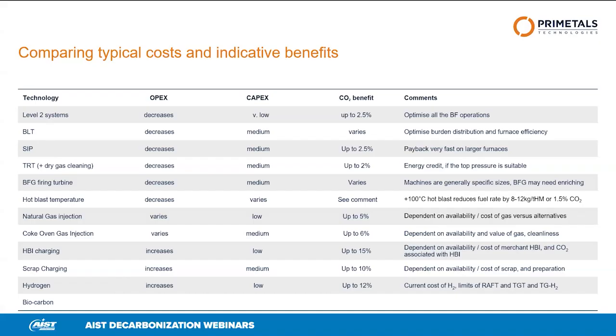Hydrogen, currently I would absolutely confirm that that's going to increase the OPEX of your plant. The capex in terms of buying hydrogen over the fence, and that's why I put low. Certainly, if you're going to generate it yourself, then the capex is going to be back in the medium range at least. And many presentations, including one of the previous AIST webinars, talked about the limits of hydrogen injection at the tuyere, predominantly based on limits of the raft and the top gas temperature and the top gas hydrogen.